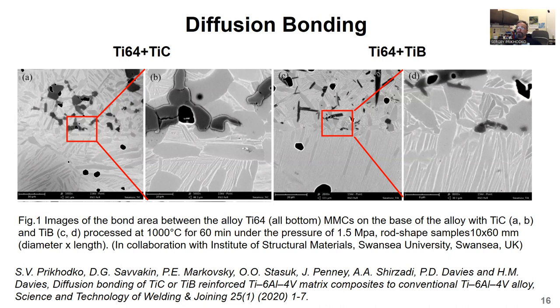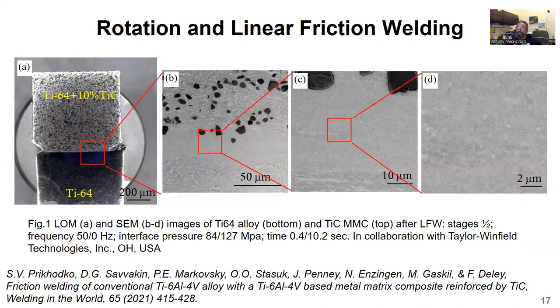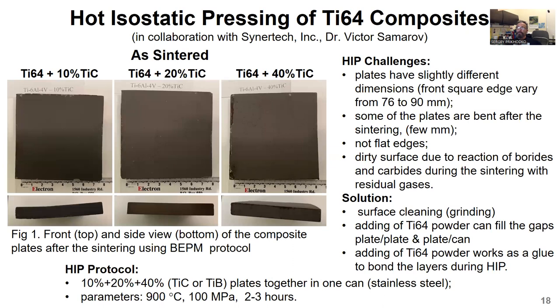Here are some of our results on diffusion bonding of composites with alloy. And this slide shows the result for bonding using friction welding. Both friction welding and diffusion bonding work great to bond the structures. However, they have obvious limitations. The major limitation of friction welding is that it doesn't affect the bulk structure of the bonded layer. Diffusion bonding helps with that, but it is limited by applied pressure and can't fix the porosity in bulk very efficiently. The hot isostatic pressing in this study was done on large size plates suitable for ballistic tests.